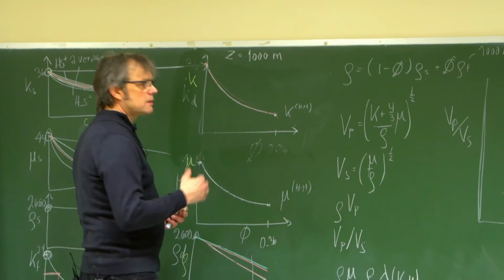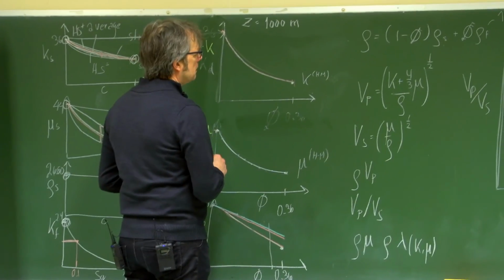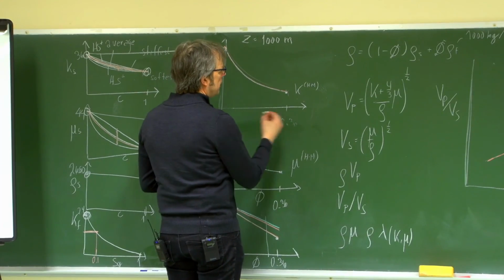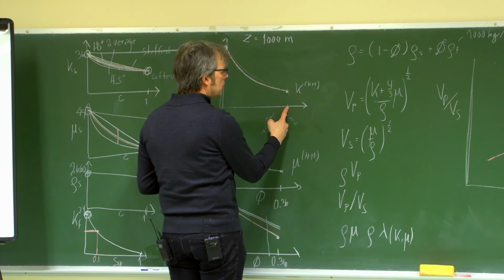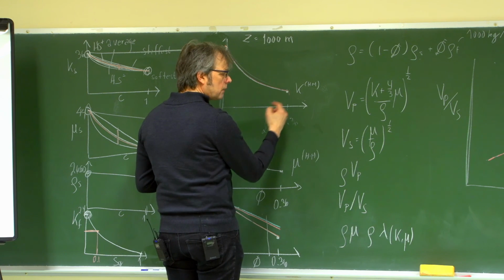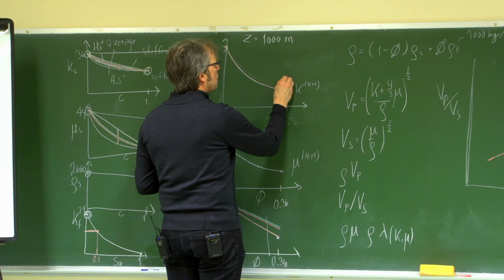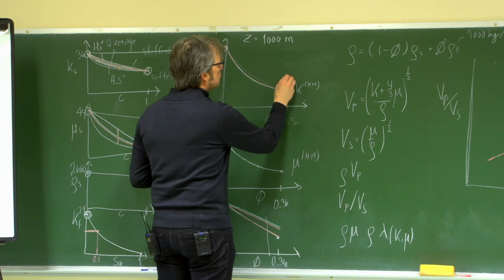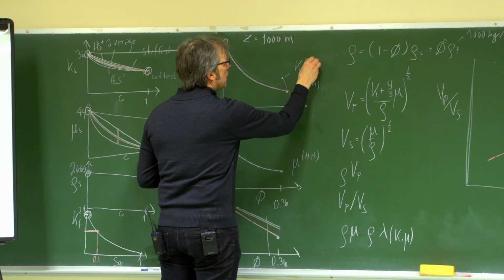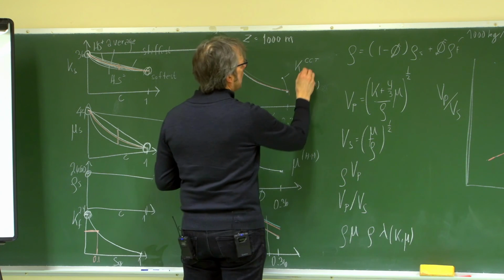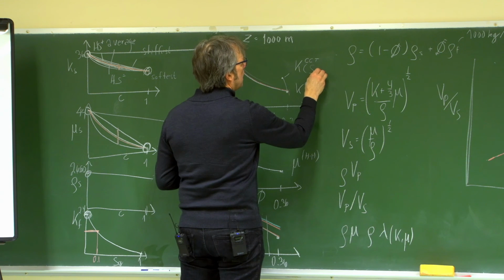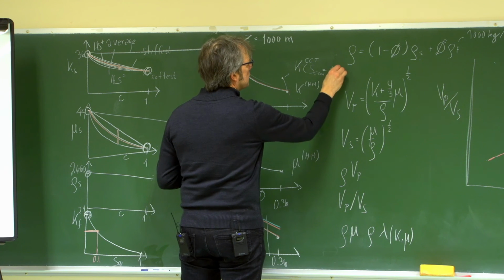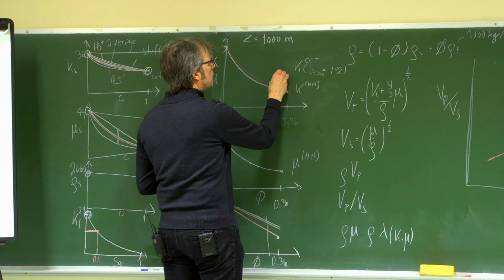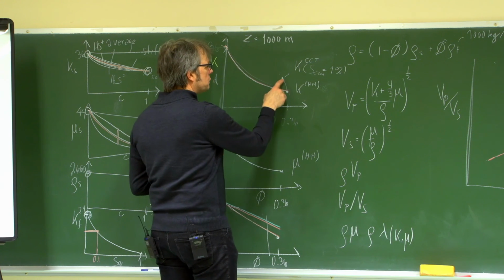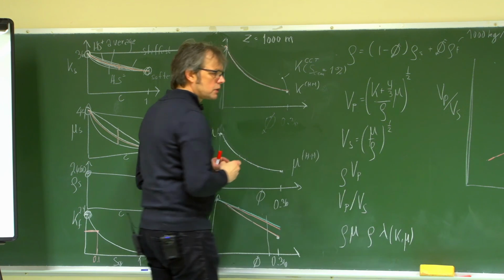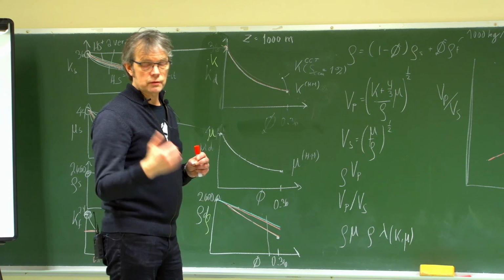Okay, so what happens if I go back to my curves over here and say that I have put some cement, quartz cement, into the system? What would happen? Yeah, I have my Hertz-Mindlin point, and then I add some cement. With the increased cement, I reduce the porosity, and we know it's stiffening the rock quite a lot, so this would jump up here. So that would be my dry rock modeling for a contact cement model with, let's say, a fraction of 1% cement. If I add 2% cement, it would jump up here, 3% and so forth. So the steps would be smaller and smaller if you increase the amount of cement. Just like when we add a gas into water. Look at the bulk modulus here.